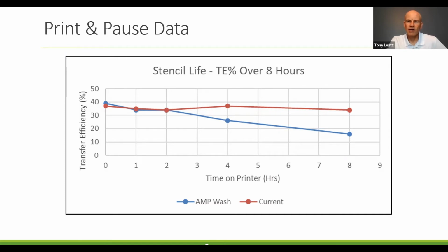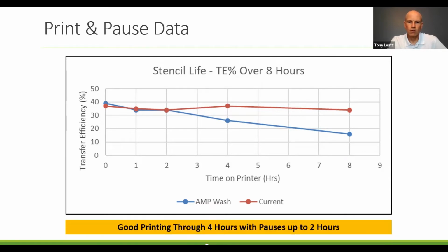The current technology paste is very stable in this test. It holds its transfer efficiency over 8 hours with pauses of 1, 2, and 4 hours. Whereas amp wash doesn't hold up to the 4-hour pause. As you can see, between hours 4 and 8, it drops off transfer efficiency pretty significantly, but it definitely handles 1 and 2 hour long pauses without any issue. So the printing was good through 4 hours with pauses up to 2 hours, which is more than adequate for any kind of application in the industry.